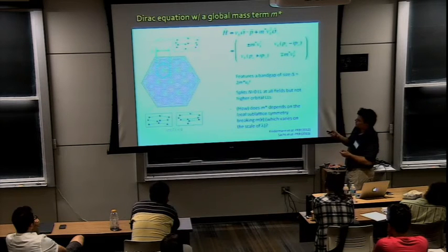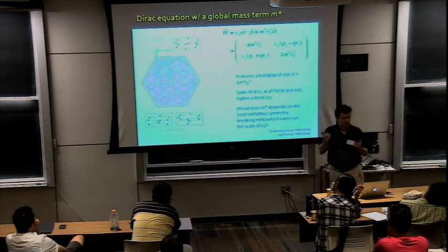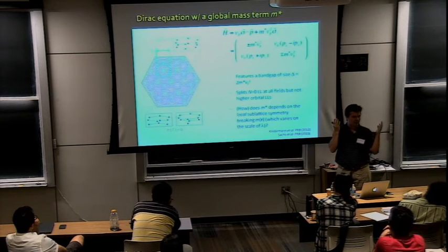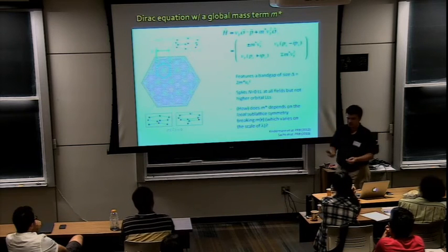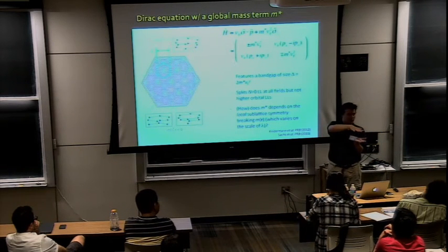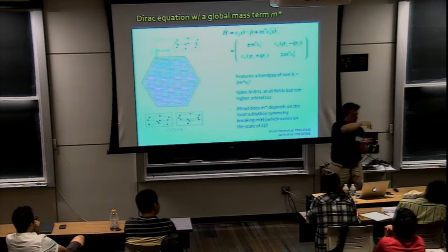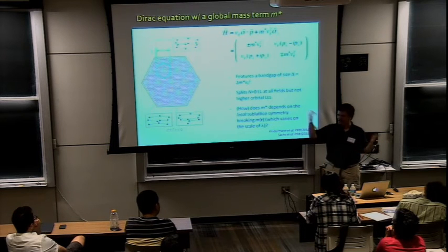Maybe in one region of graphene, locally, the simplest way of breaking sublattice symmetry is, let's say, you put graphene, let's imagine it was commensurate with boron nitride, right? So the A sublattice would be on top of the boron atoms, and the B sublattice would be on top of the nitrogen atoms. That would give different potentials to the A and B sublattices. You could break the symmetry, you would open a band gap, and have all these things that I'm telling you about.